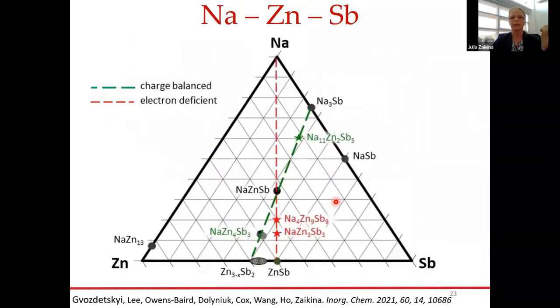So by using the hydride route, we also discovered the sodium-rich ternary phase, pictured here, sodium 11 zinc 2 antimony 5. Because it's very rich in sodium, it's very air sensitive, so very hard to characterize. But overall, with this hydride method, we really open up that phase space and discovered 5 new ternary compounds which were not previously accessible by synthesis from elements.